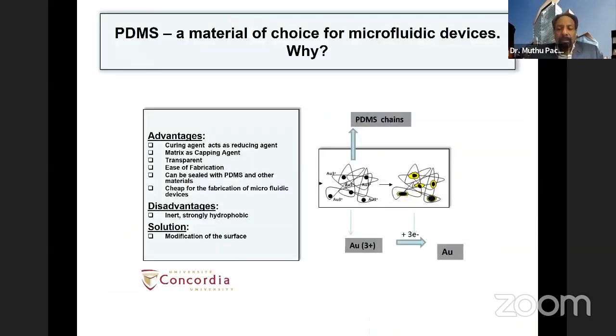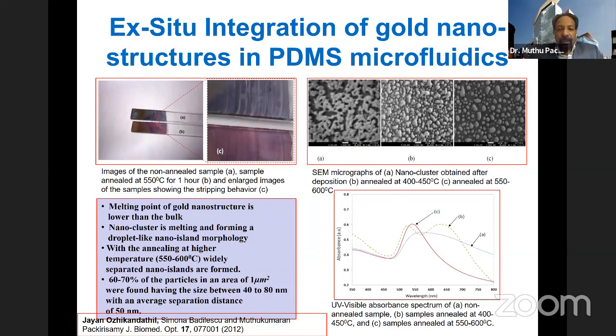We can see this when we probe it on PDMS, a polydimethylsiloxane. We all know it is very useful in microfluidics, and the reason we are using this material is that the curing agent of the polymer acts like a reducing agent for the synthesis of gold nanoparticles too, reducing the precursor of gold nanoparticles.